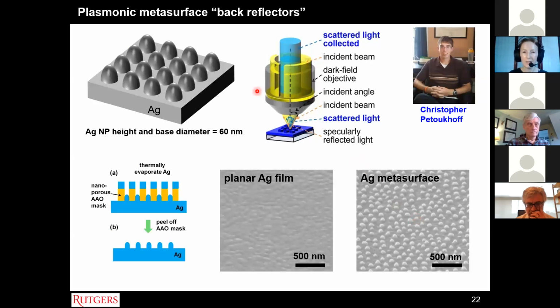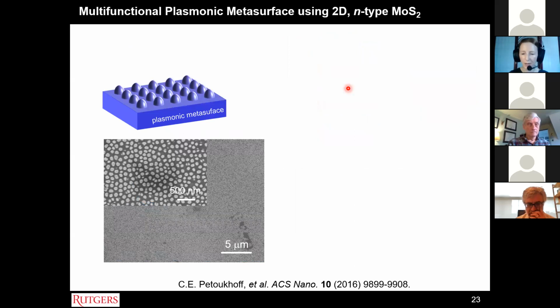And we did a lot of optical characterization using dark field backscattering to show improvements in light absorption and scattering, and to detect the plasmonic modes that were created by these plasmonic surfaces. So he did, in collaboration with Keshav Dani's group in Japan, at OIST, where he's now a postdoc.